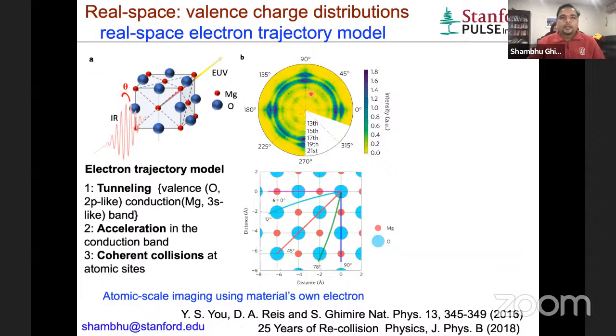So when you have the laser polarized along the cubic directions, in this case, you get maxima. And we use a relatively simple model to understand the anisotropy. And this is the picture. Essentially, we consider the electron gets tunnel excited from the oxygen valence band, which is mostly coming from the oxygen 2p, and then to the magnesium conduction band, which is mostly coming from magnesium 3s. And we do take the band motion of the electron for linearly polarized field.